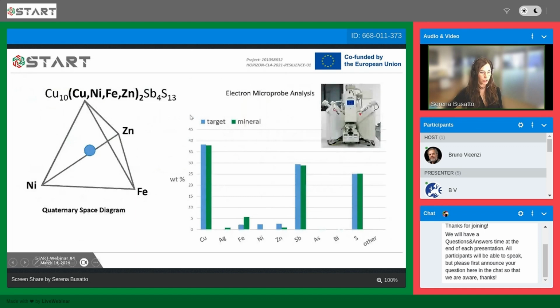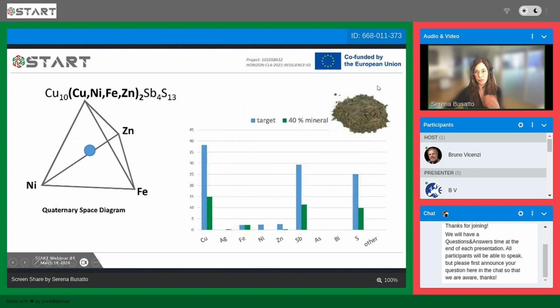Okay, here I will show you how we balance the composition of the minerals. So in green, you can see the composition of one of the mineral concentrates we received, and it was measured by electron microprobe analysis. And in blue, it's the target composition. So we identify what is the limiting element present, which is normally iron, and this sets an upper limit to the amount of mineral that we can include in our tetrahedrite if we want to reach the target composition that we selected. So in this case, it was 40%.